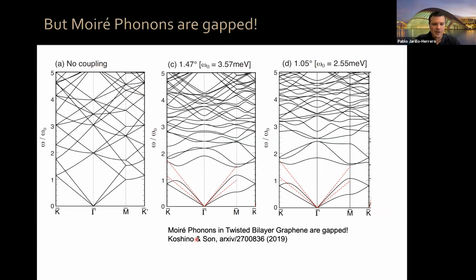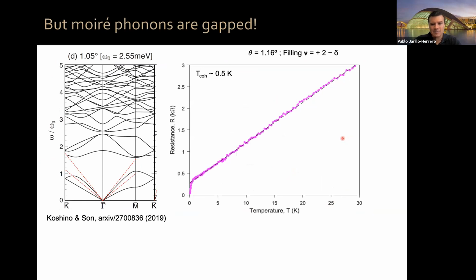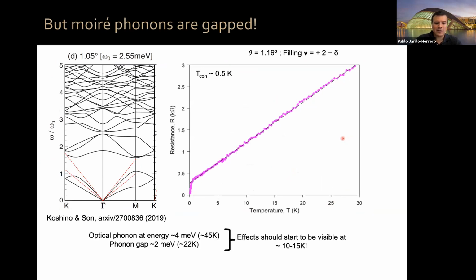So these are calculations by Koshino and Son on the phonon band structure, energy and momentum. This is for no coupling between the 2 layers. This is for some coupling between the 2 layers, in this case at twist angle 1.47 degrees. This is for magic angle bilayer graphene. And you can see there's a massive renormalization of the phonon band structure, including various gaps. So you have a whole bunch of low energy optical phonons because of these gaps, due to the coupling between the 2 graphene lattices. In particular, the optical phonon energies at the magic angle are of the order of a few millielectronvolts, with phonon gaps of a few millielectronvolts.